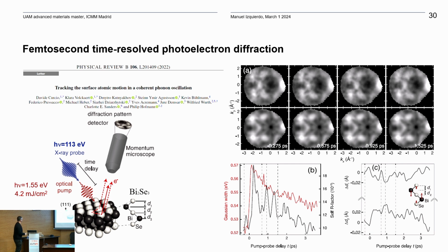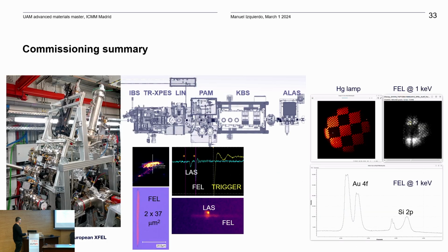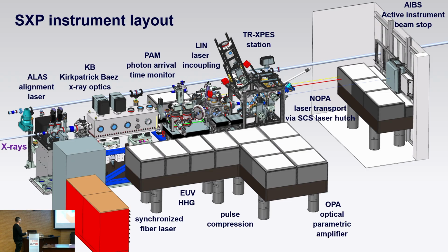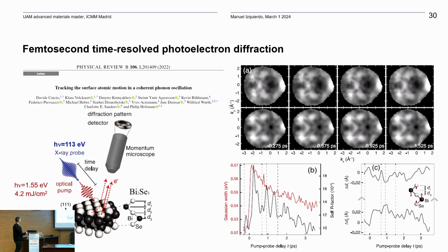The last experiment I'm going to show is the realization of photoelectron diffraction, which is the dream. Sorry, I went too quick. Okay, there you go. Again, 800 nanometer pump, 113 electron volt probe, and they used this system, bismuth selenide. What they did was photoelectron diffraction. You see here, on the one hand, the experiment, and on the other hand, the theory